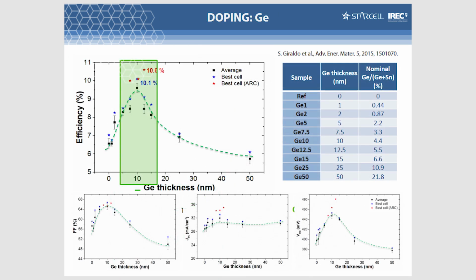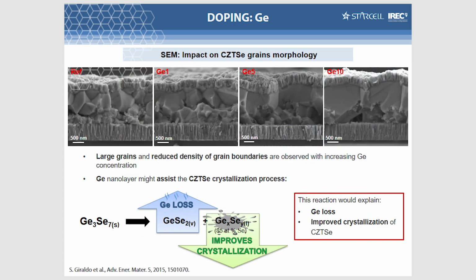Because we observed 2 or 3 years ago that including a very tiny quantity of germanium, we obtained a very huge increase in our efficiencies. And germanium is replacing tin, so in some way we have an idea that by tuning tin we can also get really huge improvement. In particular, we observe a very large VOC increment, and this is one of the main problems of kesterite.